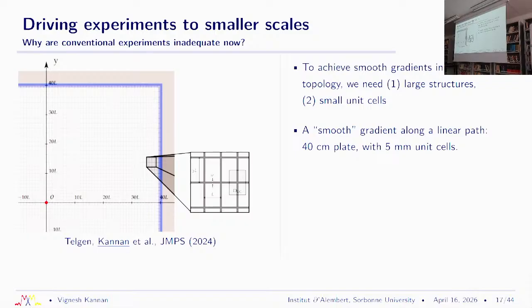So here is an example of one gradient we tried with the aluminum plate. This is a design, and you can see that there is a gradient of the unit cell architecture from a square to a rectangle up there, right? So this was over 20 centimeters, so it's a 40 centimeter plate. This is over 20 centimeters, and our unit cells are 5 millimeters, right? So if we want to play with arbitrary gradients, you will soon end up with steps, simply because we don't have infinite control on the size of the unit cell in these kind of plates.